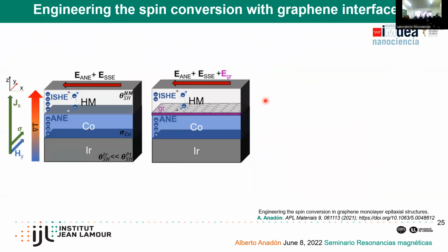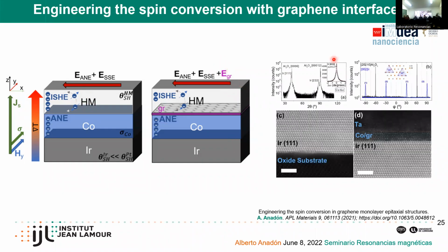The system that we took first was an iridium cobalt heavy metal, and in here we will put platinum and tantalum. And so we will compare iridium cobalt platinum with iridium cobalt graphene platinum. Here we are introducing a graphene interlayer, and we studied what graphene is bringing in terms of spin conversion to the system. Same as before, we have very nice samples with clean interfaces, small interdiffusion, and high quality.